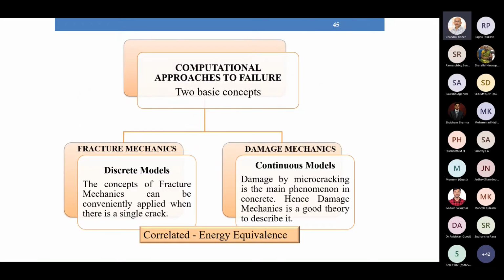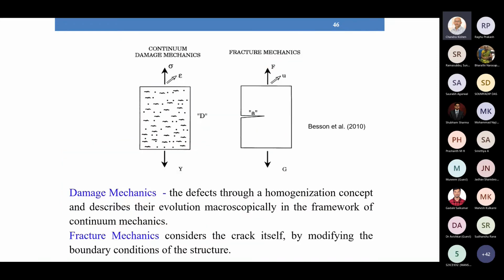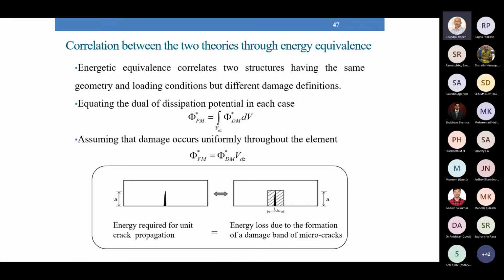Now, since we have obtained both the dissipation potentials from fracture mechanics and damage mechanics, we have tried to connect both through the principle of energy equivalence. In fracture mechanics we have a crack, and here we have a damage zone. The amount of energy required to propagate the crack should be the same as the amount of energy dissipated in a certain volume of the damage zone. So we use this kind of energy equivalence between the two systems.